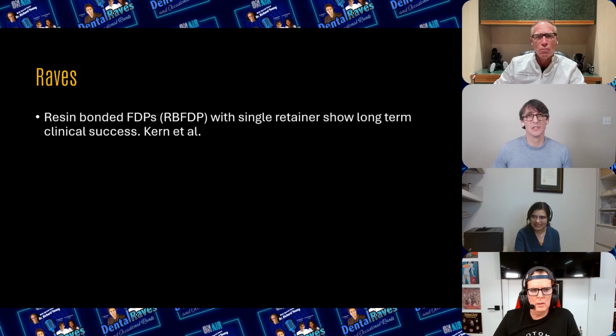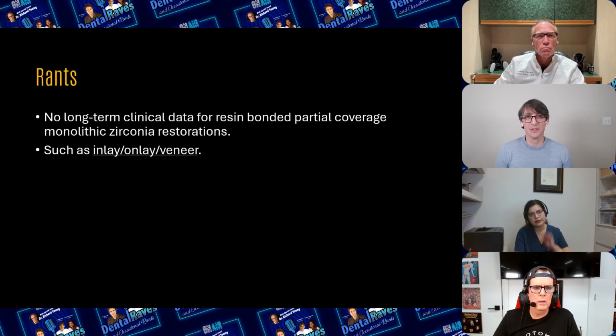Then moving on, let's rave and rant. The resin bonded FDPs with a single retainer show long-term clinical success, and that has been published in a 10-year outcome study. Great, we can rave about it. But the problem is, I'm going to rant a little and then leave the ranting to the experts, that there is no long-term clinical data for resin bonded partial coverage monolithic zirconia restorations, and I underlined it again for you, such as inlay, onlay, or veneer.